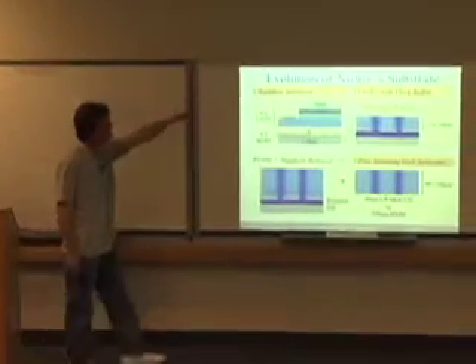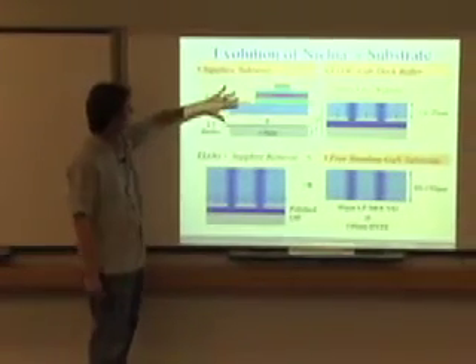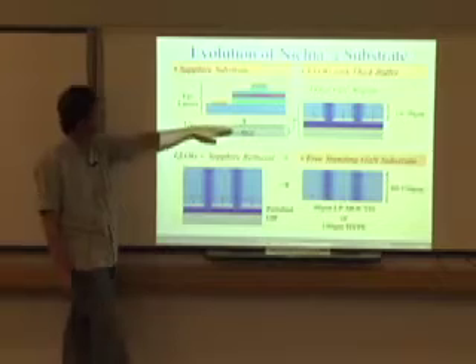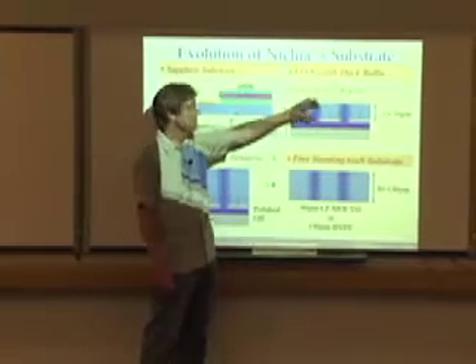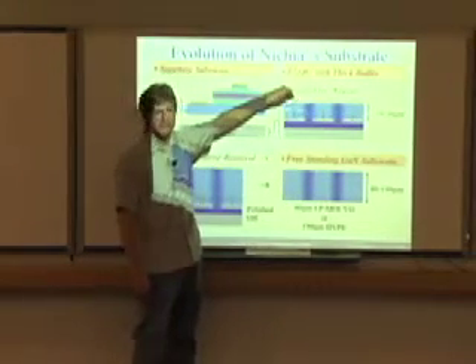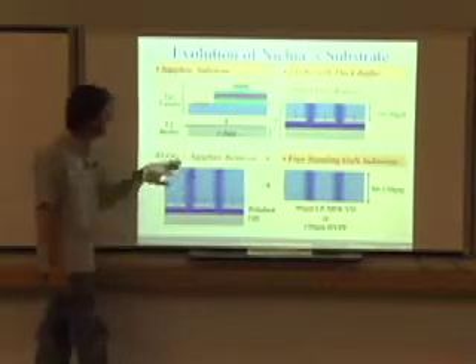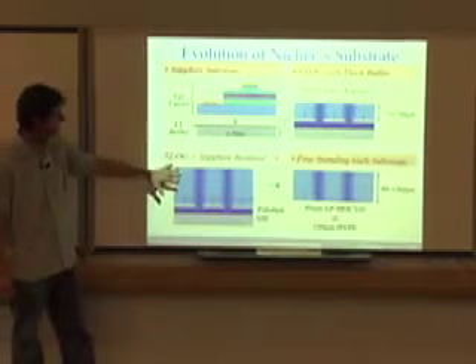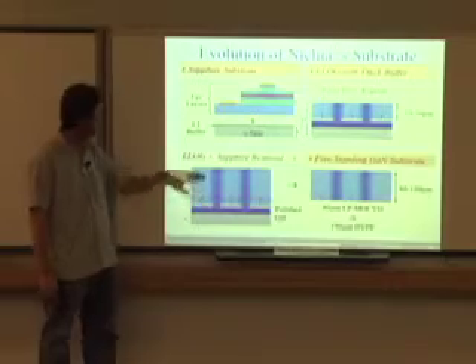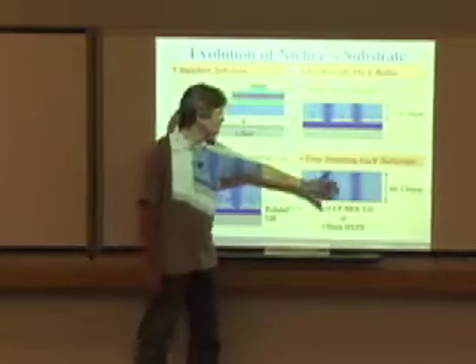So the evolution of Nichia substrate started on a sapphire substrate with this low temperature buffer layer, then went to E-log. Defect-free regions are the regions where you would make the laser structure. Then eventually they grew a thick layer on top of this with HVPE, and then polished off the substrate and were left with effectively a gallium nitride substrate.